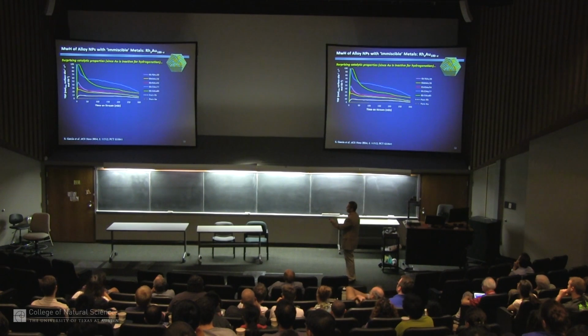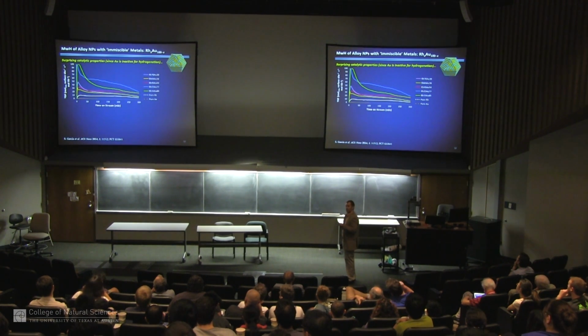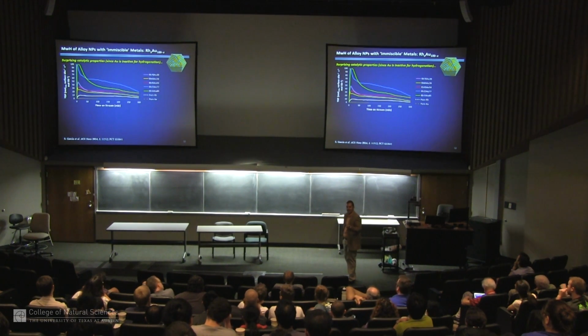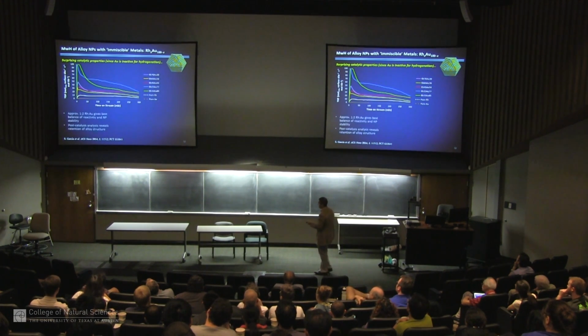When we did some hydrogenation chemistry with these, again, gold is dead. Here's our rhodium for scale. We found that all of these particles were somehow more active than rhodium itself, which didn't make too much sense to begin with because you're diluting the rhodium with gold, and gold's inactive in hydrogenation, so why is it making a more active catalyst?